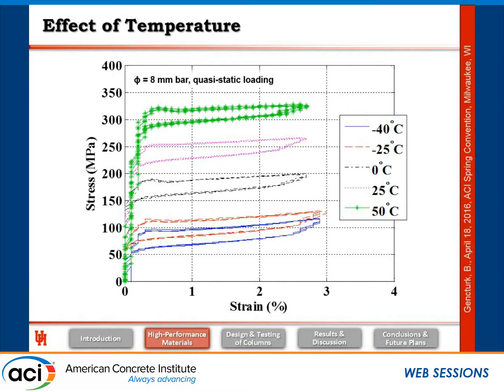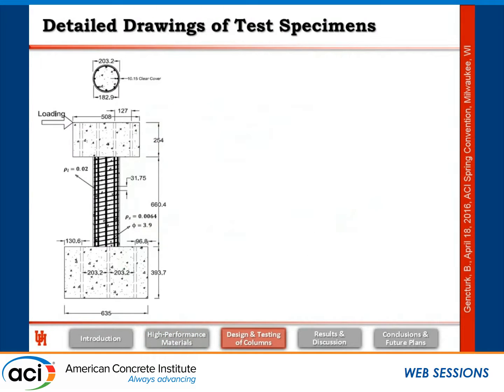At minus 40 C, which is not uncommon, you can see minus 40 in some parts of the US, the yield stress goes really down to 100 MPa, which is a concern, which we're still debating how we could address. But the nice thing, at least, is the material still shows the superelastic behavior. It doesn't rupture or do anything weird. That's all about the materials.